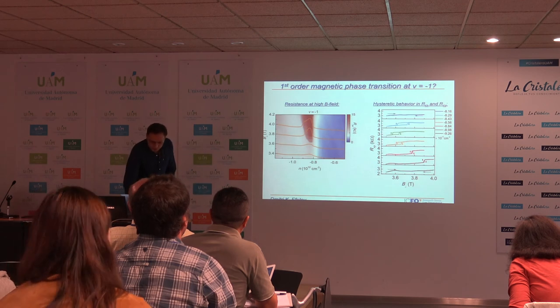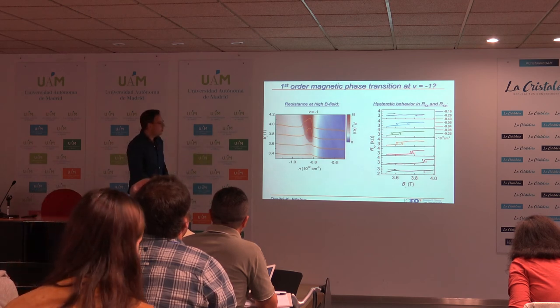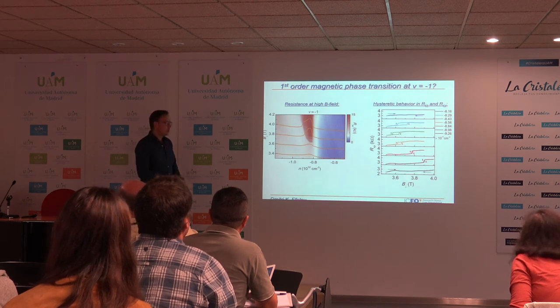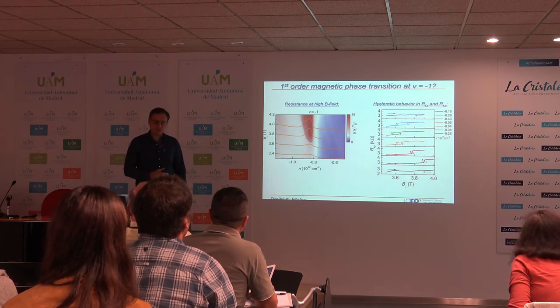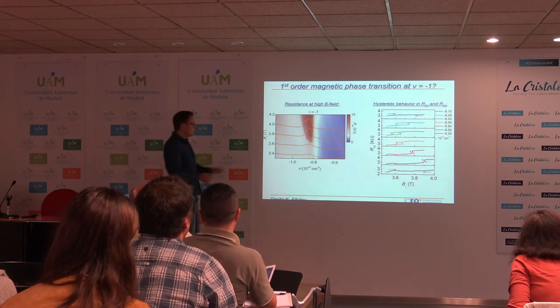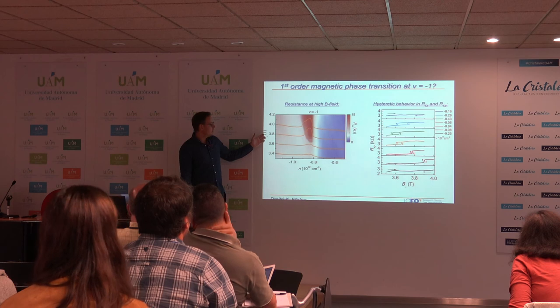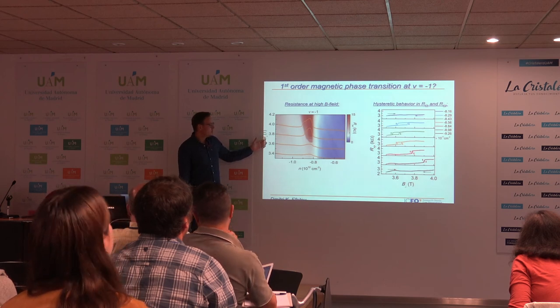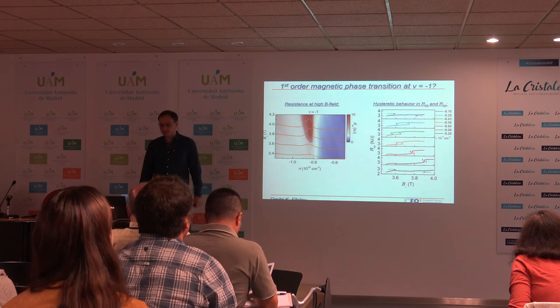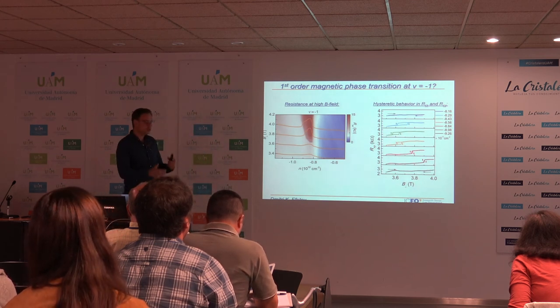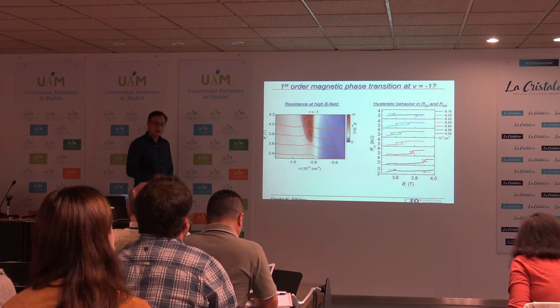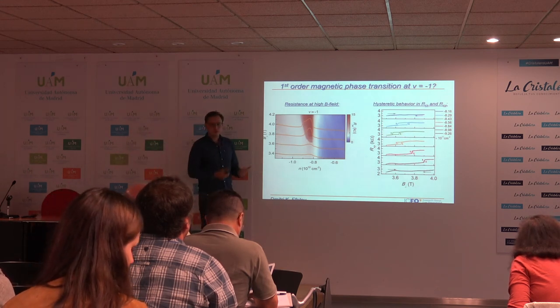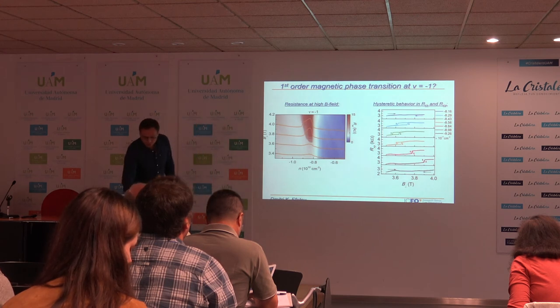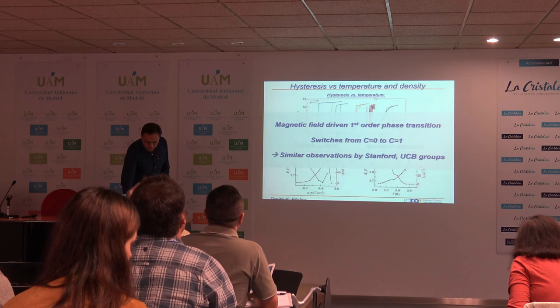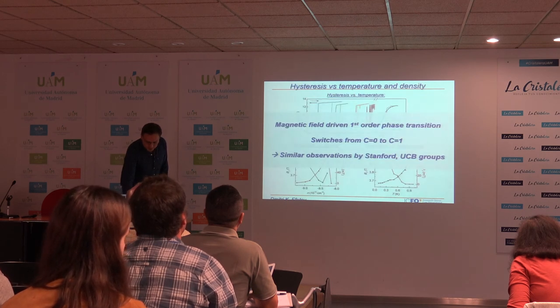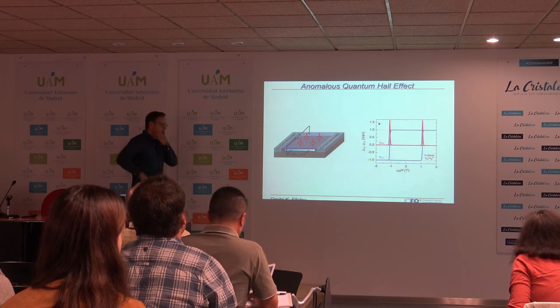So basically, we believe that there are some magnetic phase transitions happening in the system. In this particular case, the magnetic phase transition happens at finite fields, so we believe that this is probably some magnetic field stabilized magnetic transition. This is a transition which is not magnetic at zero field, but when you apply a high enough magnetic field, we induce some sort of magnetic phase. Okay, and this brings me to the last point I wanted to discuss.